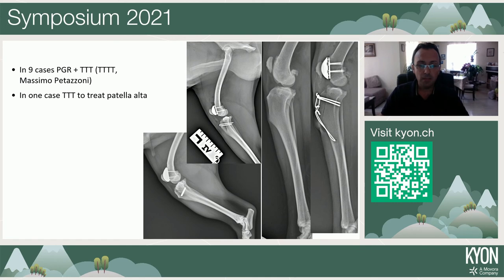So it's not surprising that many of my cases were in combination with some additional corrective osteotomy surgery. Actually, only in two cases did we apply just a PGR as a sole treatment. And it's not surprising that in these two cases we couldn't achieve stability of the patella in the trochlear prosthesis, so these cases ended up with reluxation. In 9 of our cases, a PGR was combined with some variation of tibial tuberosity transposition. In one case, a patella alta was identified as the only reason for medial patella luxation, so we had to distalize the patella first, and then we applied a PGR implant.